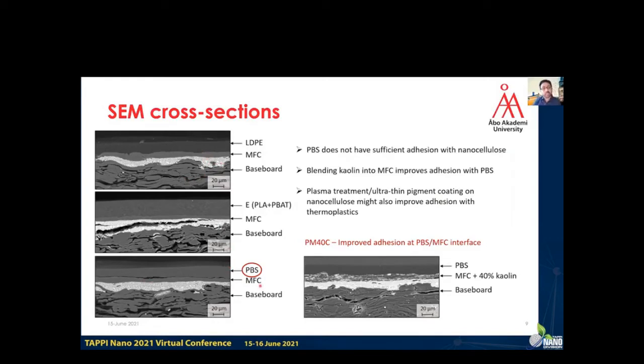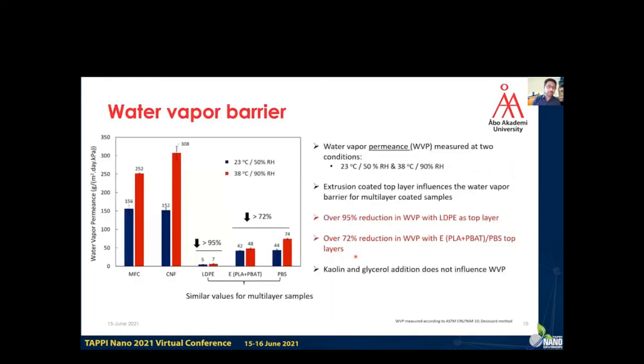And if we look down here, we see that PBS does not have very good adhesion, and one can see the layer separating. And when we blend kaolin into MFC, it improves the adhesion with PBS, like you can see in the image below. Also, a plasma treatment or having an ultra thin pigment coating on nanocellulose might also improve its adhesion to thermoplastics.